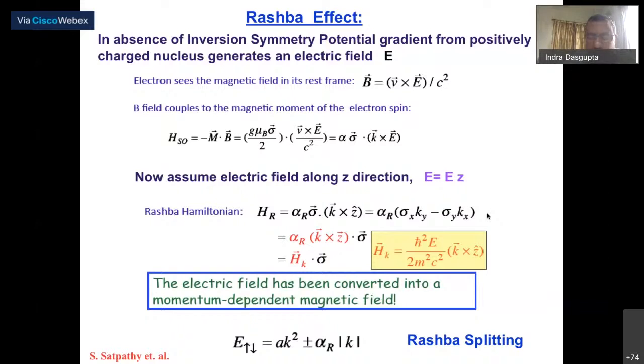But this is an electric field which arises due to a potential gradient because of broken inversion symmetry. So this is something which one should distinguish from the radial electric field of a nucleus. This is an important thing to distinguish, and it has the celebrated name Rashba spin orbit coupling. So you have essentially converted your electric field into a K-dependent magnetic field, and this gives rise to splitting of your up spin and down spin bands, and this splitting is proportional to K to linear order. It can also have higher order terms, but the first order is linear. And because of the spin orbital locking, as I'll show you, this also shows exciting kinds of spin textures, which play an important role in